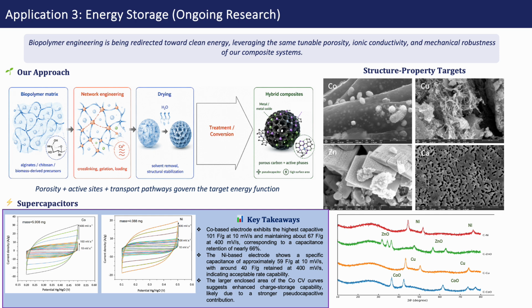at 10 millivolts per second and around 67 farads per gram at 400 millivolts per second, corresponding to nearly 66% capacitance retention. So the nickel-based electrode shows a lower but still interesting response with around 59 farads per gram at 10 millivolts per second and about 40 farads per gram at 400 millivolts per second. So overall, these results suggest that the same bio-based platform can be redirected from pollutant adsorption and nutrient release toward electrochemical energy storage.